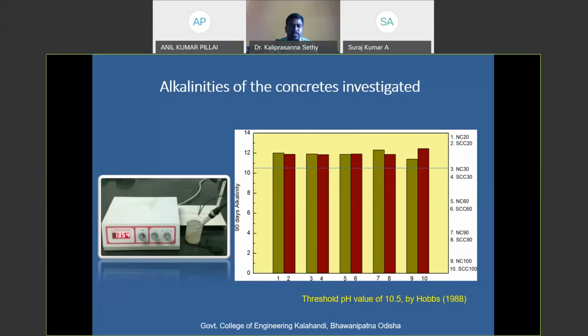Here is the alkalinity or pH test we performed for this developed concrete. As you know, if the pH value is more in your concrete, the passive layer is stronger, which is nothing but a protective layer to your reinforcement to avoid corrosion. So for that we have checked the 90-day pH value of all our samples. This is the result we found after testing. The core of the cubical samples we have taken and ground up to 300 micron, and we mixed with distilled water, and using this digital pH meter we tested all these samples for their pH value, and you can see all the values.